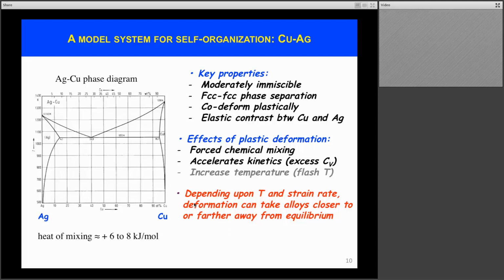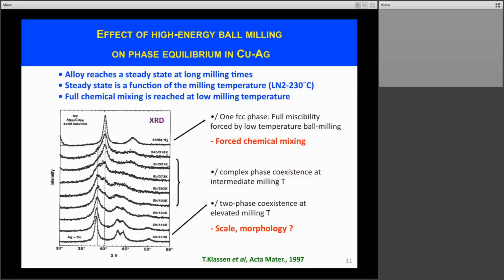And so the first take-home message here is that, depending upon the temperature and the strain rate, deformation can take alloys closer to equilibrium by accelerating their kinetics, or it can take them farther away from equilibrium through this forced chemical mixing. And so to illustrate this point here, I reproduced some results obtained by Bob Averbeck and one of his collaborators, Thomas Klassen, where you see different X-ray diffraction traces here of copper-silver that has been ball milled for a long time. So ball milling is one common method to apply severe plastic deformation to materials, and so we've used it quite a bit over the years in our laboratory.